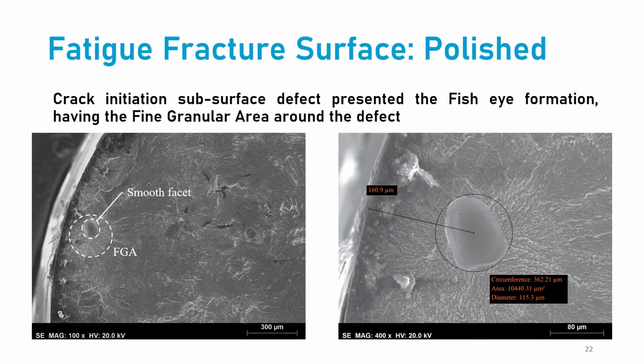Now, if we take a look at the crack propagation at the subsurface defect, we can see the fisheye formation, which is normally associated with a very high cycle fatigue regime. In this case, we have a specimen that initiated at a smooth facet that then had propagation in the fine granular area. We can see here this shape associated with the fisheye formation. Again, we have the distance to the free surface and the radius which was quantified of the smooth facet.